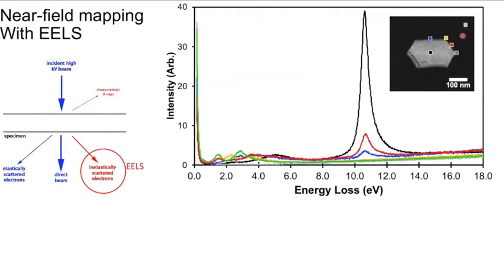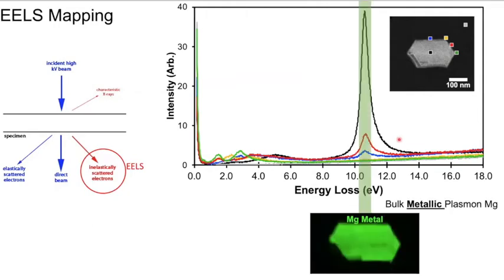So if I send my electron beam away from the particle, it's the gray line, and it's basically just the tail of the zero loss peak and then absolutely nothing. If I put my beam inside the particle, I see this giant peak at about 11 eV that is not a localized surface plasmon resonance. In fact, it's a bulk plasmon. The condensed matter physicists here know exactly what I'm talking about. It really is just a signature of the metallic nature of that magnesium. And that's super useful because it gives us an accurate map of where the metal is. This is not a property that we can easily probe in silver or gold or even in copper. It's really useful in magnesium and in fact in aluminum as well.